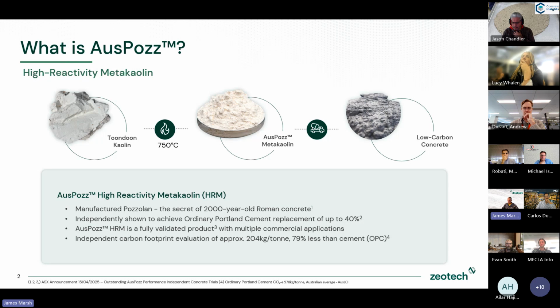We've been doing a lot of testing. As you'll see, I'll show you some results, but we've been using cement replacement amounts up to, in fact, 60% now, but up to 40%, it's still giving very good results. At 60%, it probably matches GP cement. It's fully validated. We've tested it in probably 100 different mixes now. And we've also had independent verification of the carbon footprint, which is just over 200 kilos a ton, so about 80% less than ordinary Portland cement.